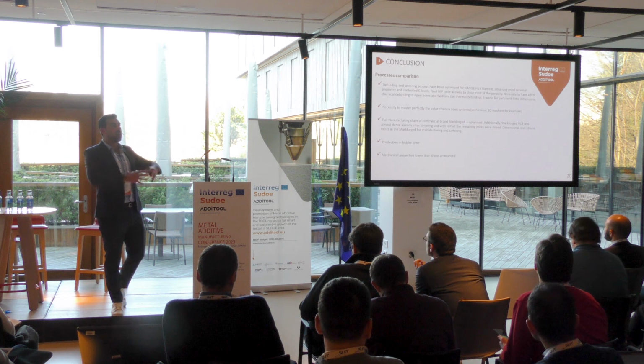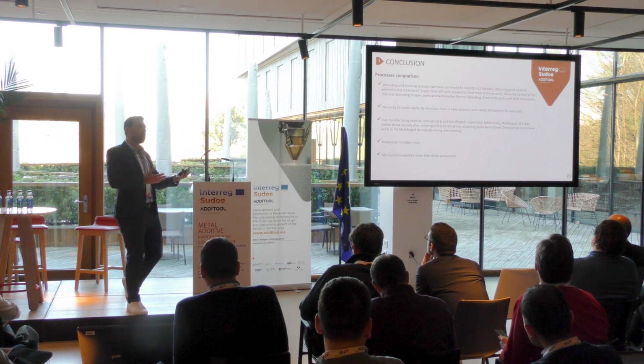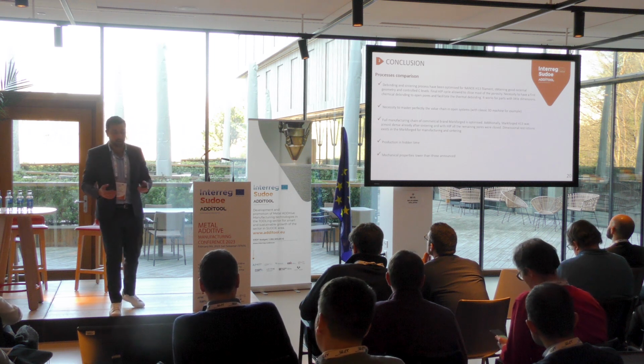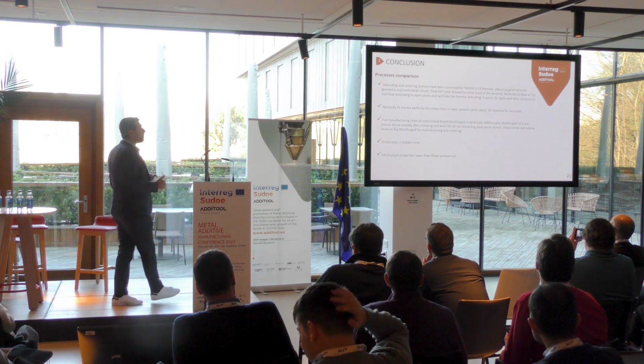And it works great for parts with little dimension. When we have a big part, a massive part, you will have a little bit of deformation and some cracks that can appear. So for a small part or thin plate it works, but bigger it's more complicated. And it's necessary also to master perfectly the value chain if you have an open system.